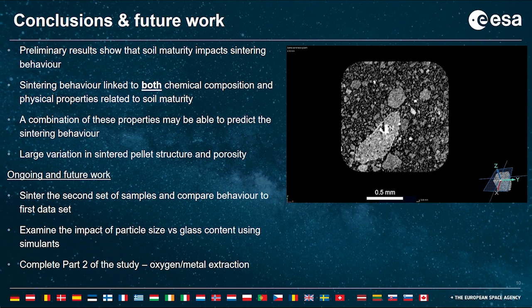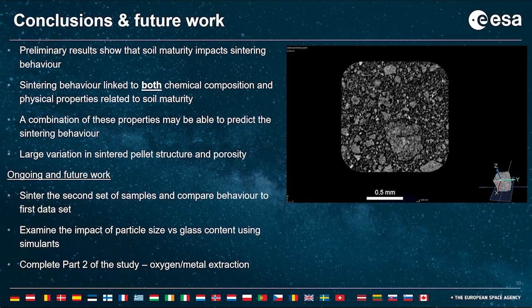So then to conclude the work and talk about the future work, the preliminary results show that the soil maturity impacts the sintering behavior, and the sintering behavior can likely be linked to both the chemical composition and these physical properties. A combination of these properties could be used to predict the sintering behavior of material in situ based on quite a small data set of information about the material. And there's large variation in the sintered pellet structure and porosity.